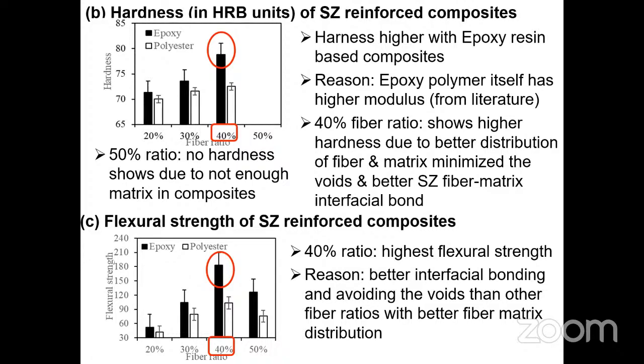When it comes to the flexural strength of Sansevieria zeylanica reinforced composites, again the 40% ratio shows the highest flexural strength, and epoxy resin with 40% fiber ratio gives the highest flexural strength. The reason is better interfacial bonding and avoiding voids compared to other fiber ratios, with better fiber-matrix distribution.